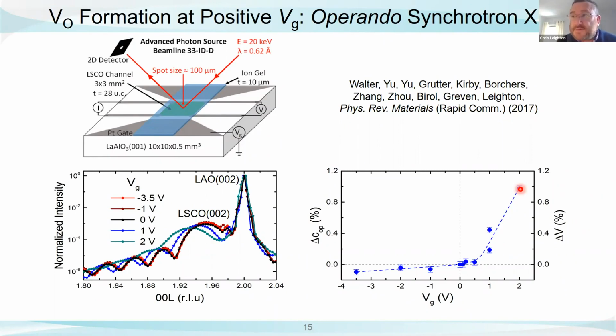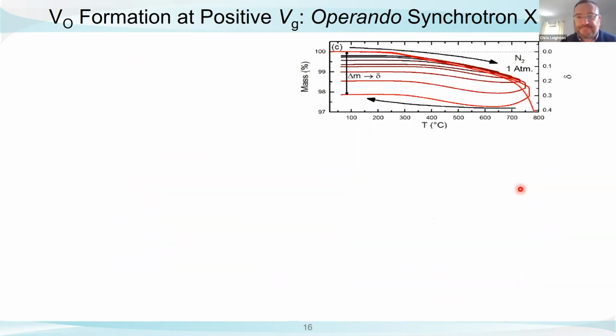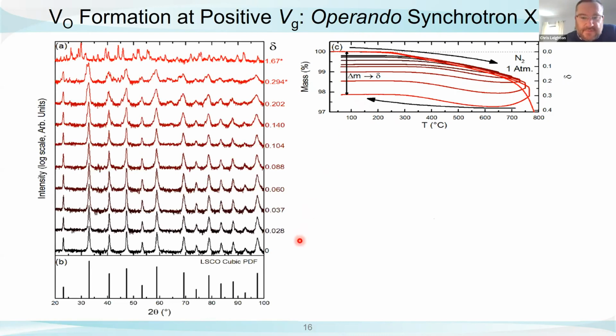So when we saw this, our first thought was: is LSCO one of the many oxides that undergoes this famous chemical expansion effect, where oxygen vacancy formation increases the size of the unit cell? So we checked this using a bulk technique called thermogravimetric analysis. We're basically just measuring the mass. We're warming it up in a reducing environment. We lose a certain amount of mass, which tells us what oxygen deficiency we have. We do that progressively to higher temperatures. We end up with a whole series of samples where we have known oxygen deficiency.